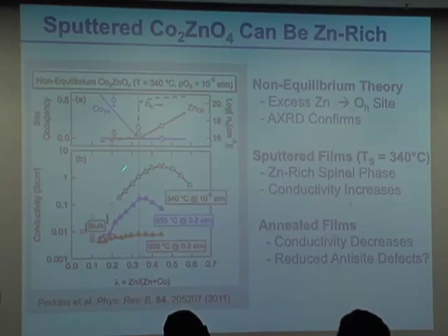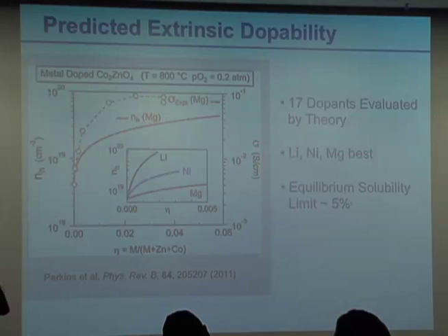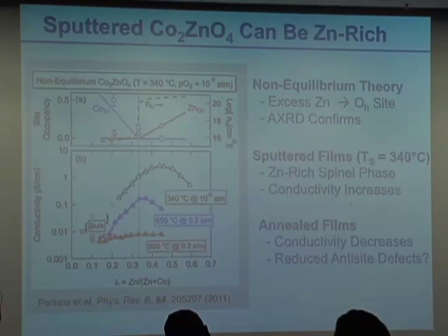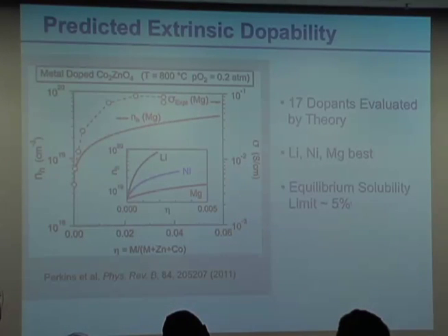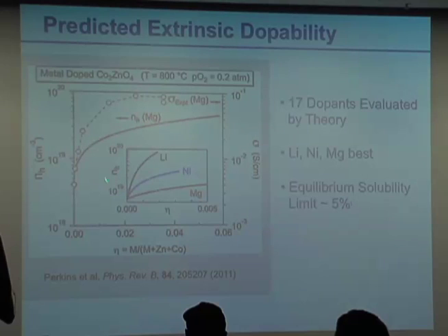And as we anneal these films, we see the conductivity decrease, and we think the anti-site defects are reversed. One of the things we then asked is if we could put this, this is kind of a self-doping, having the zinc go to the tetrahedral site. But what if we took other dopants? Here we looked at 17 different dopants. Three very good dopants that theoretically should increase the hole concentration are lithium, nickel, and magnesium.